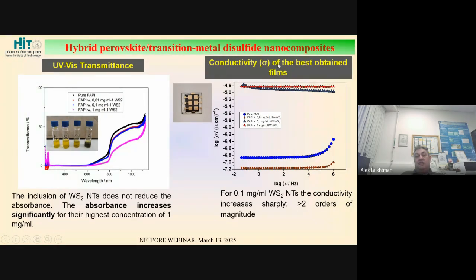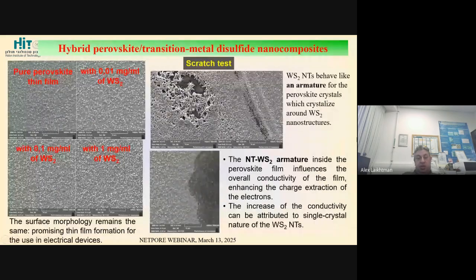They measured the conductivity of these films, the mixture of perovskites with nanoparticles, and they obtained that, for example, for the concentration of 0.1 milligram per milliliter of WS2 nanoparticles in the perovskite mixture, the conductivity increases very sharply, more than 2 orders of magnitude.